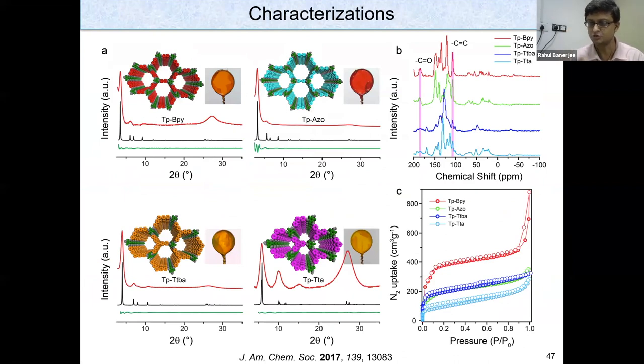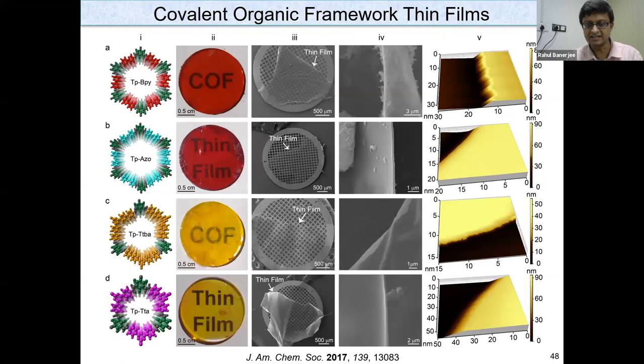So you don't make the covalent organic framework in the beginning. You just crystallize them one after another into the surface itself. So just simple mix and match. You take the amine on the top layer, put the aldehyde on the bottom layer, it comes in contact, forms the interfacial crystallization, and gives you very nice, once again, thin films. The thickness of this is much thinner. Over here, I'm showing you a little bit thicker films for visualization purposes, but we could make roughly from 50 nanometers and go up. Self-standing ones are still half a micron thick.